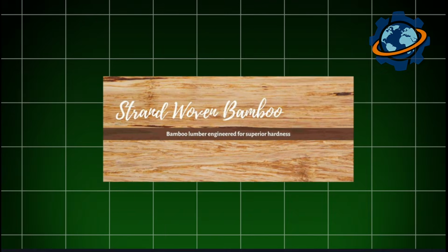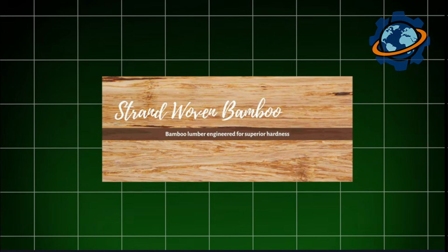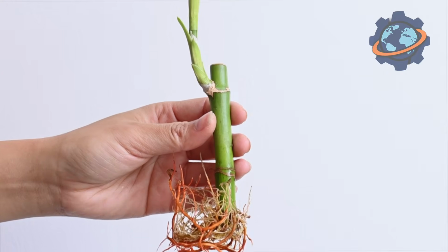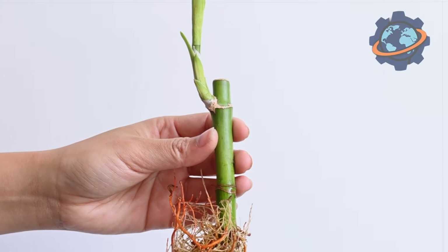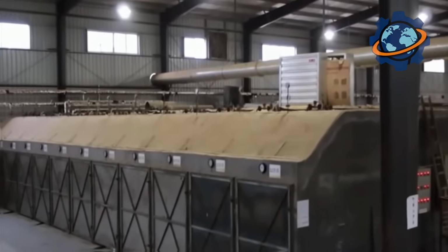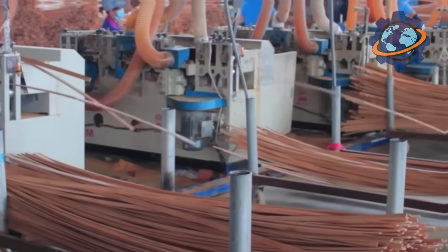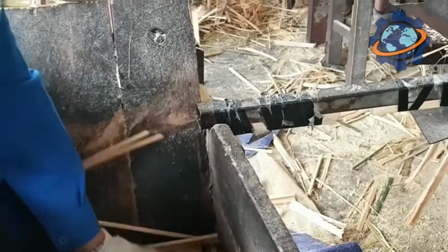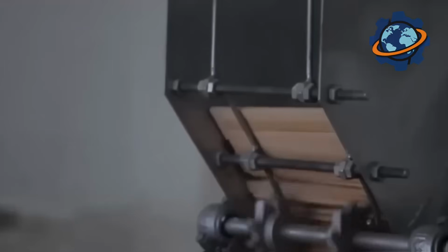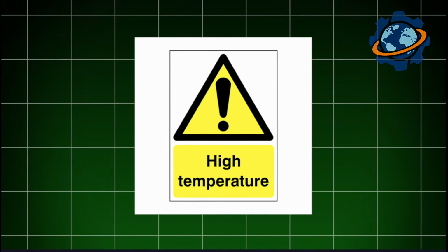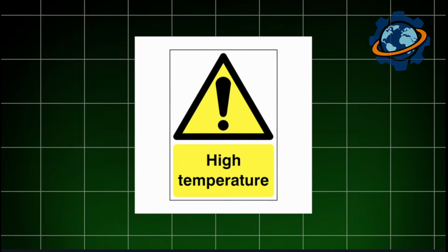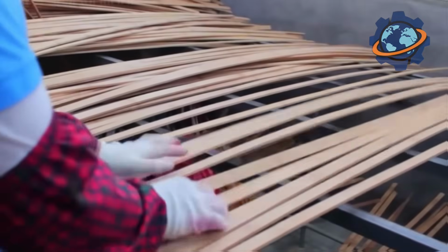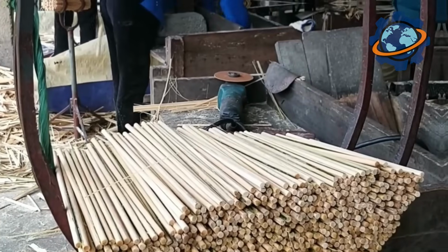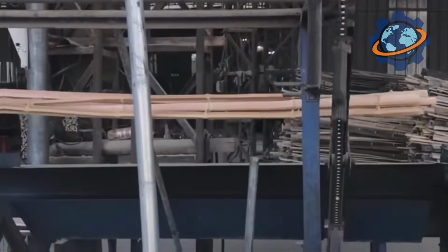But the real marvel is the strand woven technology. Here, the bamboo planks are not just glued together, but completely shredded into long fibers, mixed with an environmentally friendly resin, and loaded into huge steel presses. Under infernal pressure, reaching 3,000 pounds per square inch, and high temperature, this mass transforms into an extremely dense, monolithic block. The hardness of such flooring on the Janka scale can exceed 5,000 units, making it more than 3 times harder than oak, and more resistant to scratches and dents than most traditional wood species.